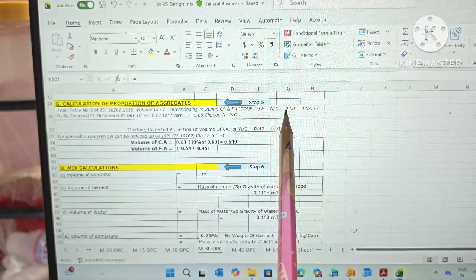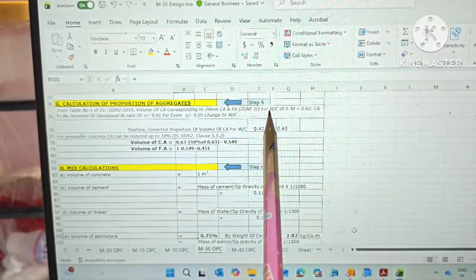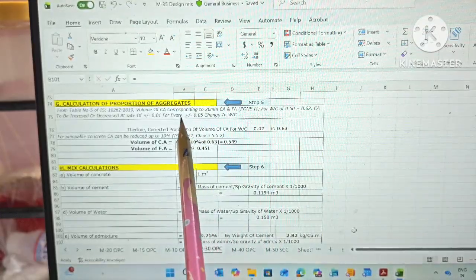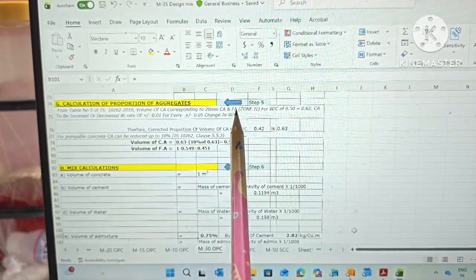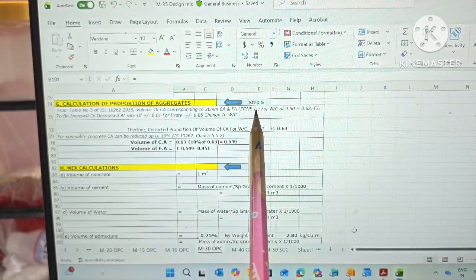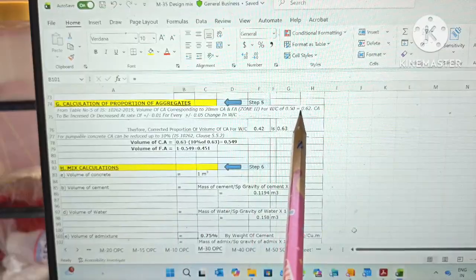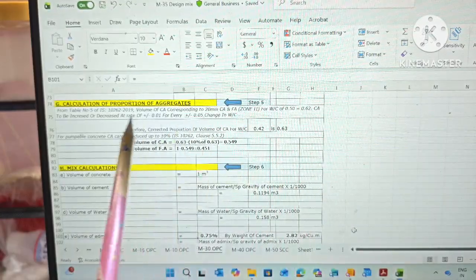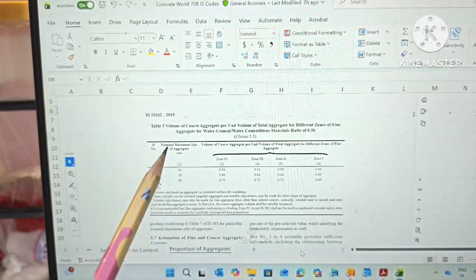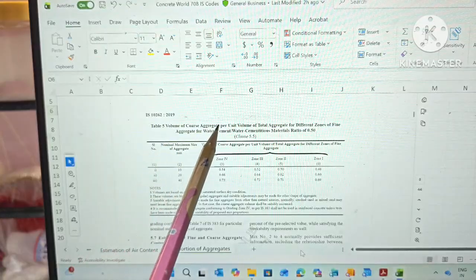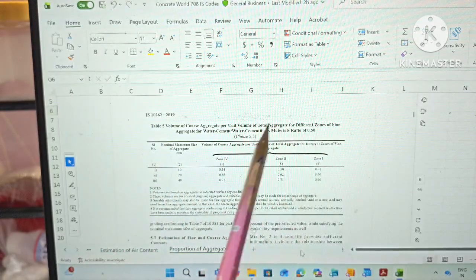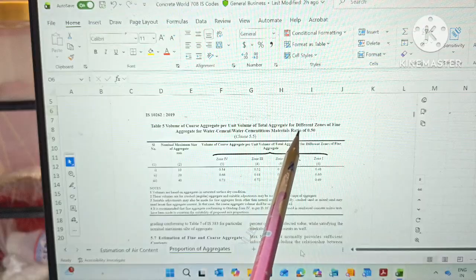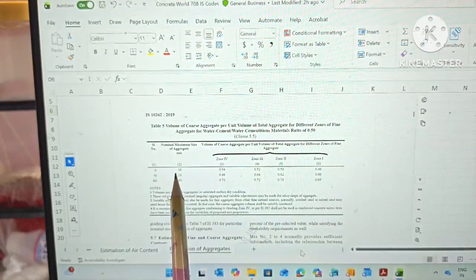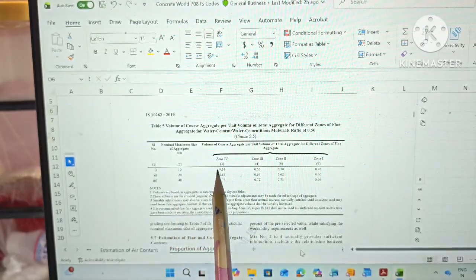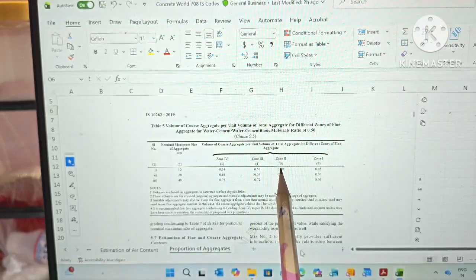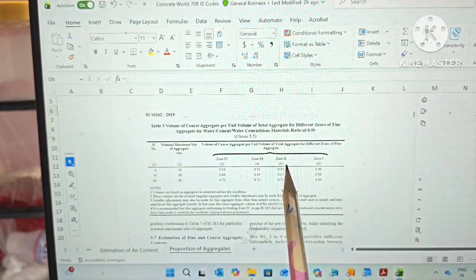See, when the water cement ratio is 0.5 and the zone of sand is zone 2, your volume of coarse aggregate is 0.62. Now moving to table number 5. Friends, this is table number 5: volume of coarse aggregate per unit volume of total aggregate for different zones of fine aggregate for water cement ratio of 0.5. Maximum size of aggregate is 20 mm. If you go along the line of 20 mm for zone 2, the volume of coarse aggregate is 0.62.